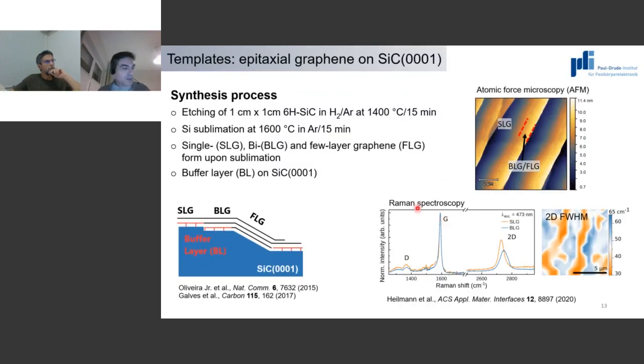And so I go now to the part where I explain what type of samples we have been studying. We wanted to have a large-scale template for starting. And in our opinion, the best template you can get is epitaxial graphene on silicon carbide, because it's wafer scale and single crystalline, so it's ideal for this type of investigation. Instead of using, for instance, graphene grown by chemical vapor deposition on copper and then transferred to another substrate, where you have a transferred material with a lot of contamination, so you don't really get a nice van der Waals surface. So we've chosen the epitaxial graphene on silicon carbide.